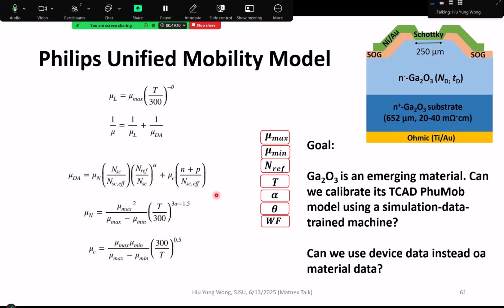So this is the example we want to do. Now we have 7 parameters. We have mu max, mu min for this equation, reference T, the temperature of the measurement, and also the work function. 7 parameters, right? Another important thing is that we don't request the experimentalist to come up with a 4-point probe measurement, a test structure to measure the mobility, so that we get the mobility exactly. We still just use a device that was fabricated, but that device depends strongly on the mobility because of this drift region, right? Can we calibrate it?